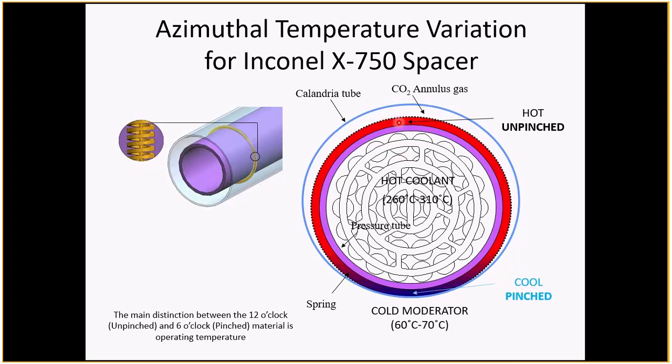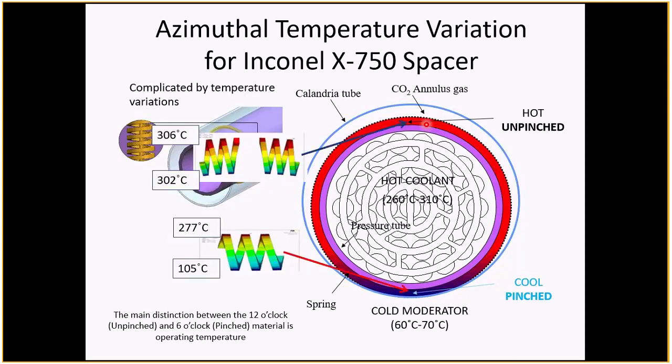You've got all these processes I was talking about, because nickel has a high reaction cross-section. It's absorbing neutrons, it's producing (n,p) and (n,gamma) reactions and all kinds of things. And all of this contributes to heating up this spring relative to the other stuff around it. So you've got the heat from the channel, and you've also got the fact that it's self-heating.